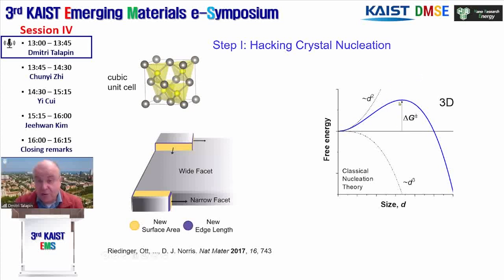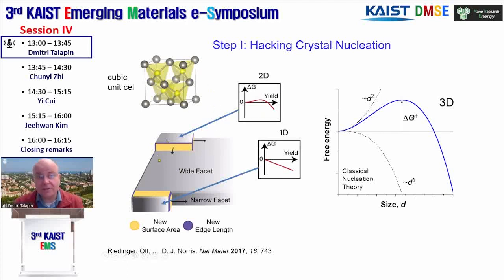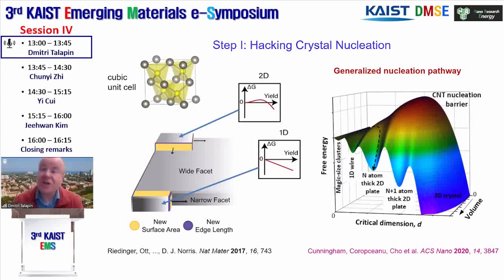But it turned out that there is a lot of dynamics in the pre-nucleation stage, and along certain trajectories, the pre-nucleation clusters experience large shape fluctuations. And if they develop shape anisotropy, then something interesting can happen. So instead of growing layer after layer by nucleating new layers at the relatively large extended surfaces of these pre-nucleation clusters, they can switch to the growth of two-dimensional structures, by one-dimensional nucleation of thin stripes at the surfaces of narrow facets of this dynamic pre-nucleation cluster. This idea was first introduced in 2017 by David Norris' group at ETH in Switzerland, but later we realized that it can be something much more broad in general.